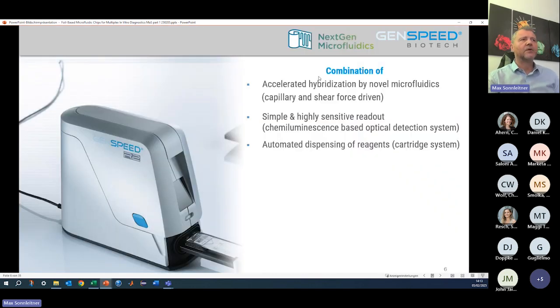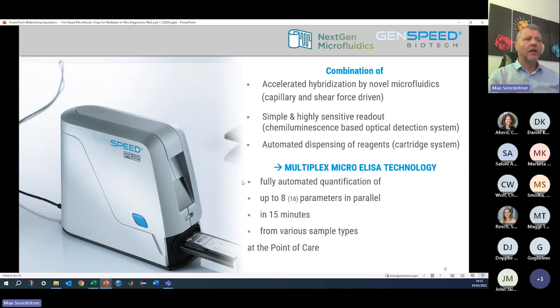And these are the advantages that we have. We combine the accelerated hybridization reaction using the microfluidic structure, because there are capillary and shear forces. So there is a much higher probability for the biomolecules to bind and interact with each other than with an ELISA in your ELISA plate in the instrument, for example. And we combine that with a very sensitive chemiluminescence-based optical detection system, and also with an automated dispensing system of the reagents using piezo membrane pumps. And this all ends up in a multiplex microELISA technology.